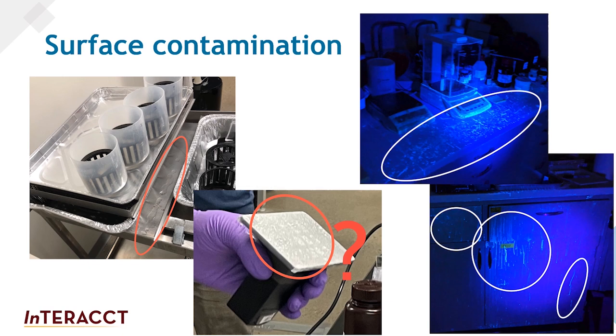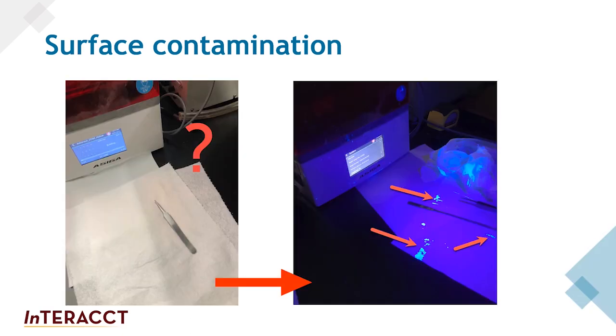Surface wipe sampling performed in the lab showed several non-detects, but a few contaminated spots that exceeded the internal surface limit, and visually there was no difference between the perceived contamination of the non-detects versus the hits. Here's an example of the difficulty of detecting surface contamination by sensitizing resins during VPP work.